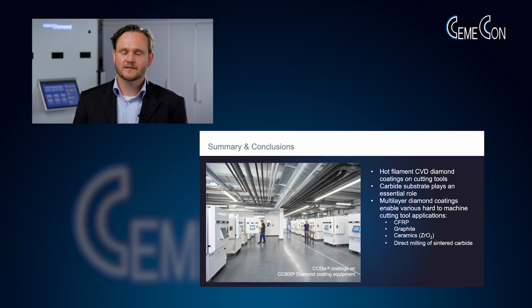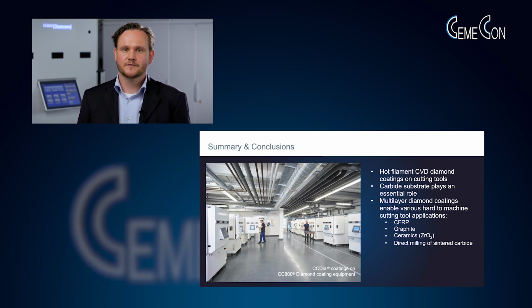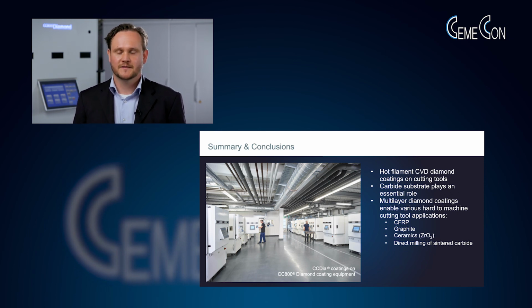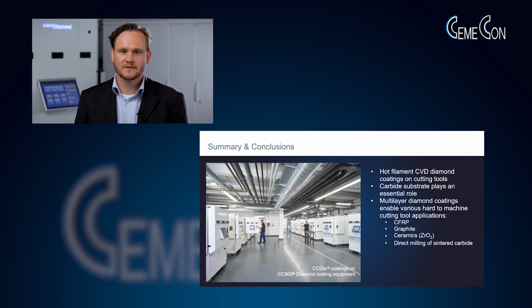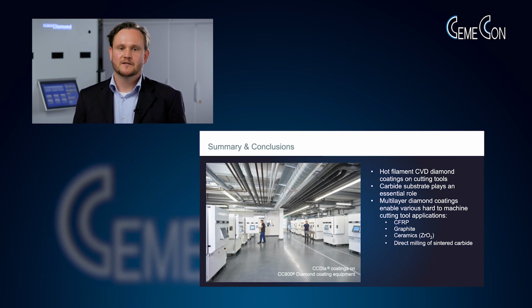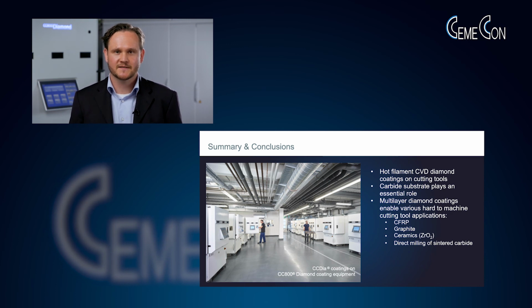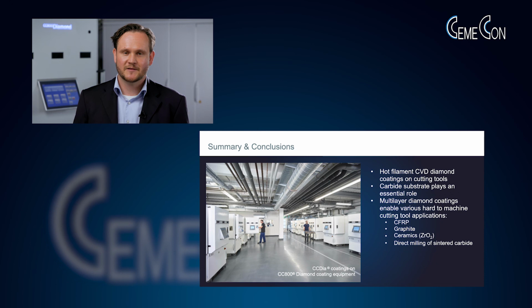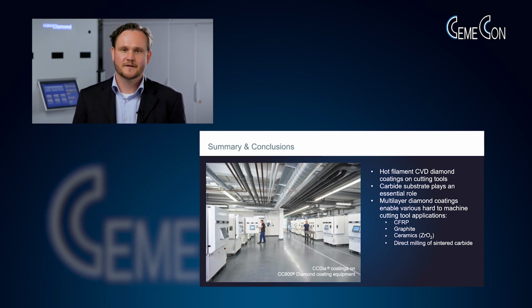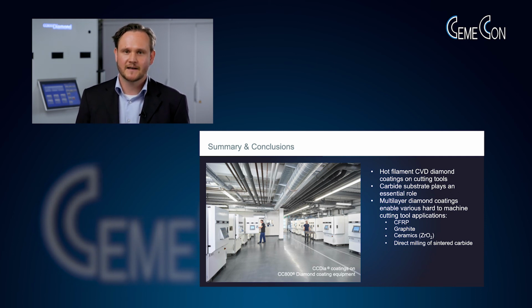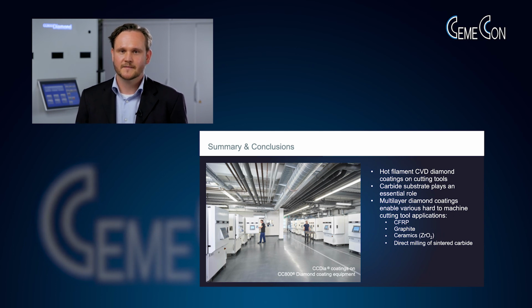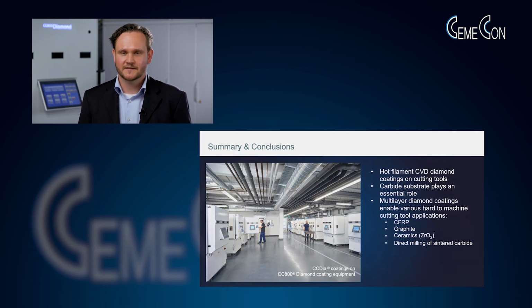With this, I would like to summarize and conclude my talk. I've introduced to you the basic principles of hot filament diamond coating. We've looked at the special role of the cemented carbide as a substrate on cutting tools. We saw that by morphology engineering, we are able to enable multilayer CVD diamond coatings, and these coatings can be used in various application cases where we are dealing with very hard to machine materials. These include machining of CFRP material in the lightweight industry, graphite, zirconium oxide based ceramics, and last but not least, the machining of sintered carbide.